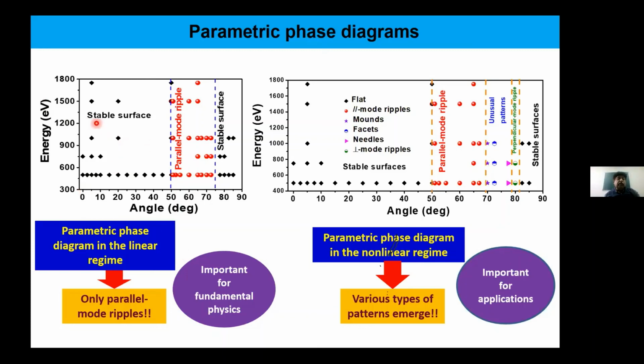So what we get to see is a stable surface. That means a flat, stable surface where no patterning was observed. Instability, as I told you, means pattern formation. Instability got set in at 51 degrees for all these incident ion energies. We got to see parallel mode ripple formation starting from 51 degrees up to nearly 75 degrees or so, and then beyond that, at even higher angles, the surfaces became flat again for all ion energies.